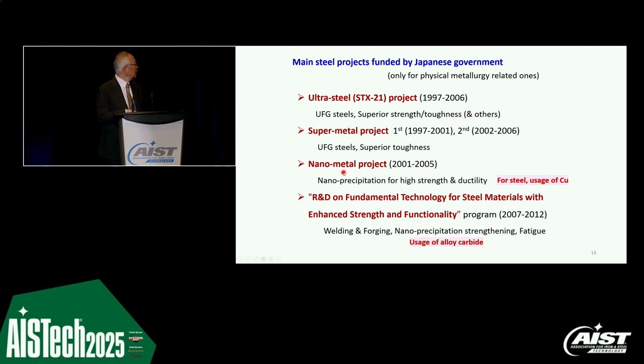And after this project, we had another project, the nanometal project, in the early 2000s. So this is nano-size precipitation used for high-strength steels. Mainly copper is used a little bit more for better strength. And later, R&D fundamentals for forging and also welding. And for forging materials, medium carbon steel, they use alloy carbide, mainly vanadium.